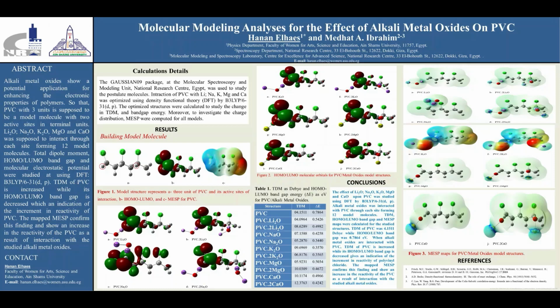The total dipole moment of polyvinyl chloride was 4.1511 Debye, while its HOMO-LUMO band gap energy was 0.7864 electron volt. When lithium, sodium, potassium, magnesium, and calcium oxides are interacted with polyvinyl chloride, its total dipole moment is increased while its HOMO-LUMO band gap energy is decreased, which gives an indication of the increment in reactivity of polyvinyl chloride.